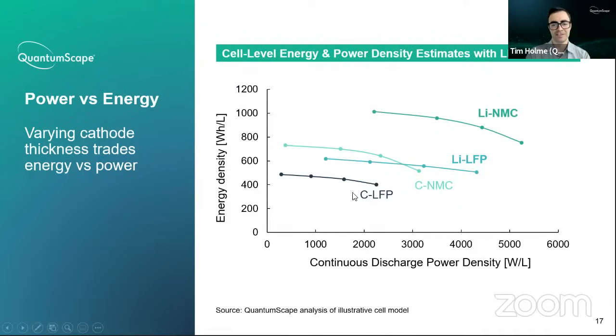So then if you change this carbon host material to lithium for LFP, you can increase its energy density as well as the accessible power, just as you can if you replace the hosted anode for NMC with a lithium metal anode. You can also increase its energy density and power density. So I think that's pretty interesting that you could get the energy density of LFP into an interesting range relative